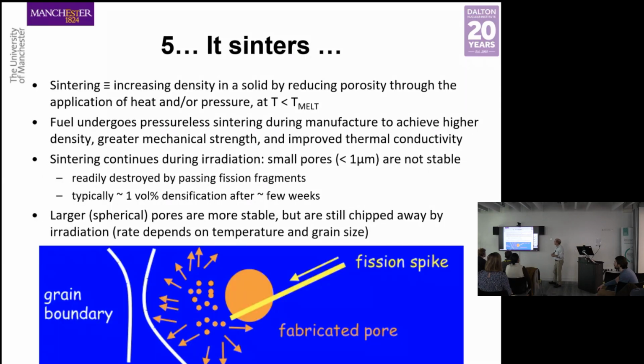It sinters. Sintering is part of the manufacturing process. It's part of a process where we manufacture all kinds of ceramic materials. We take our nice ceramic, we bake it, and it becomes that characteristic hard material. We call this sintering. Sintering is a major part of the manufacturing process, but it doesn't stop there. As soon as we put the fuel into the core of a reactor, the sintering that we started when we made the fuel in the first place just continues. And the fuel continues to get denser and denser.